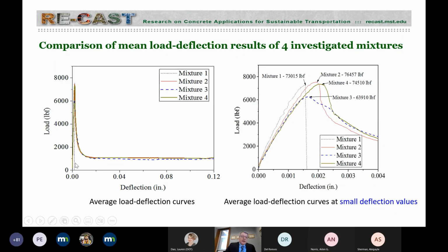So if you look at very, very close, the initial part of this curve over here, that's what is shown on the right side. You have mixture number 1, which does not have any fibers. And once you reach ultimate flexural strength, you lose capacity immediately. And then you have mixture number 2 was 4 pounds. The number 3 was 5 pounds, and number 4 was 6 pounds per cubic yard. And you see the load deflection and the gradual reduction of load carrying capacity.